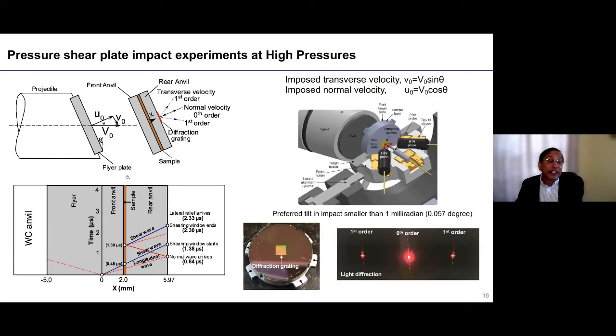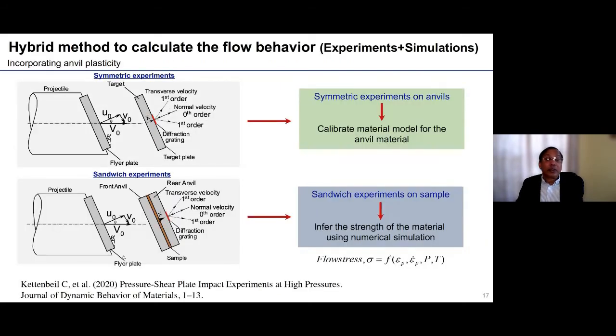As I mentioned, we designed the experiment so that we can obtain the maximum shearing window in the sample. The sample is being sheared after being brought to a nominally constant pressure. But the problem still remains that we are exceeding the Hugoniot elastic limits. So what do we do? What we are interested in is introducing this new variable, the pressure, as the flow stress as a function of strain rate, pressure, and temperature. So how do we include this?